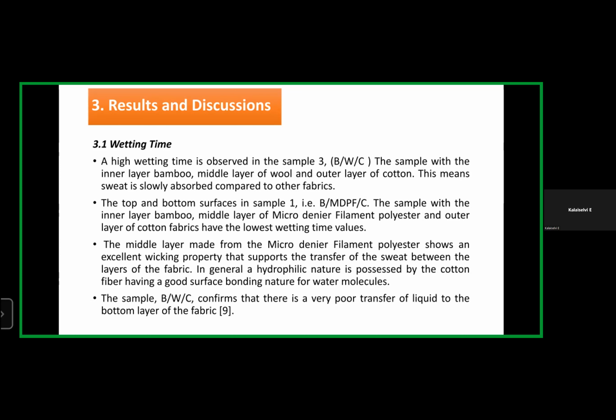The top and bottom surface in sample 1, the sample with the inner layer bamboo, middle layer microdenier filament polyester, and outer layer cotton, have the lower wetting time. If the wetting time is lower, that means good wetting time is observed. The middle layer made from the microdenier filament polyester shows an excellent wicking property that supports the transfer of sweat between the layers of the fabric.